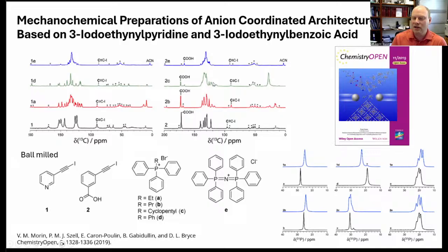And of course, we do this all in conjunction with diffraction when possible, but I'm highlighting most of the NMR aspects today. In the middle here, compound 2, just a different donor, showing you another example of the same thing, showing you the different spectra we can get upon mechanochemical formation of these halogen bonded cocrystals. On the bottom right are similar types of spectra, but this time for phosphorus. So you can see in these salts on the right here, we have a single crystallographically unique phosphorus, for example. And so those phosphorus spectra on the right here have much fewer peaks, less overlap, and clear changes in the spectra when you form these cocrystals mechanochemically.